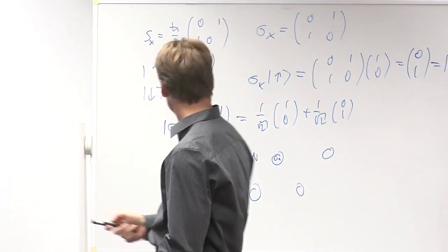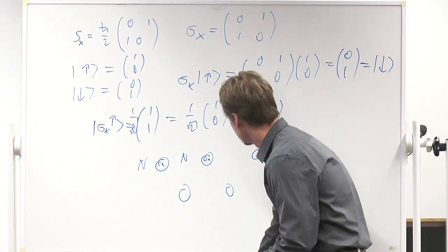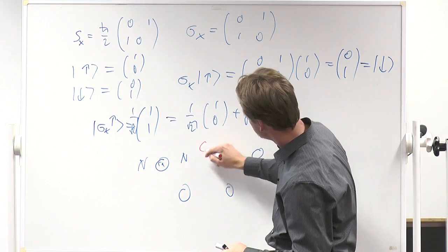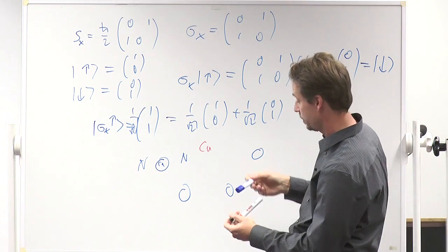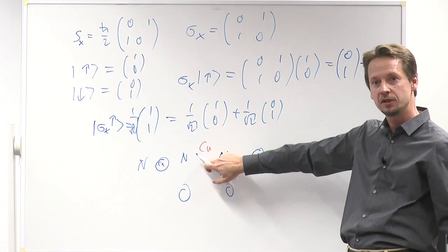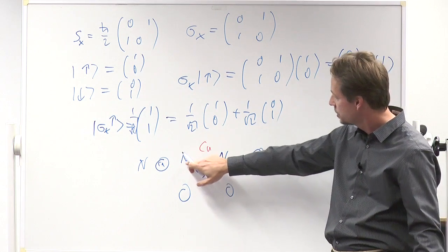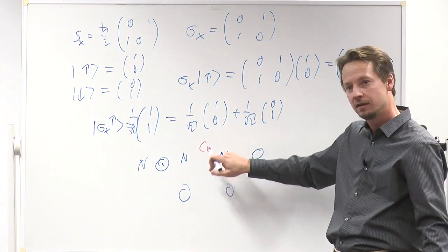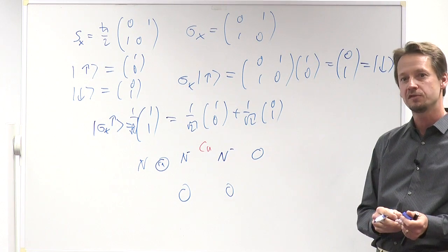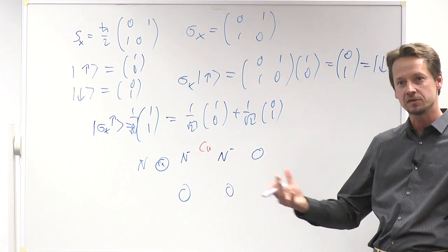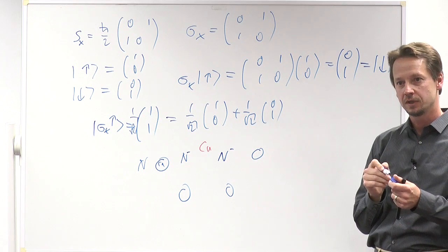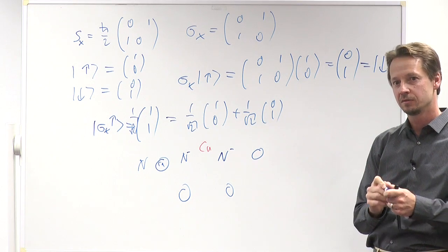It is lowered because it actually sits on this copper binding site here. It sits like this. I don't know if I have a DFT calculation in here. So it replaces one of the copper atoms that used to be there in this copper nitride. And so it has these nitrogen atoms nearby. And these nitrogens are negatively charged. And so it sets up something that we call a crystal field, local electric fields. So this environment here matters very dramatically for these effects. Right? It's not an atom in free space, basically.